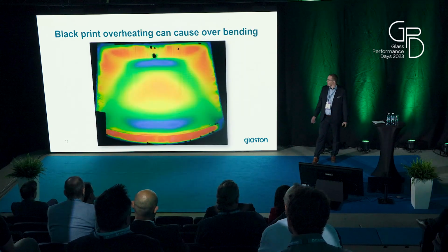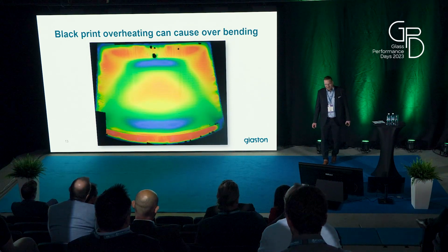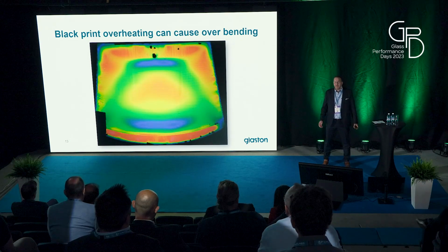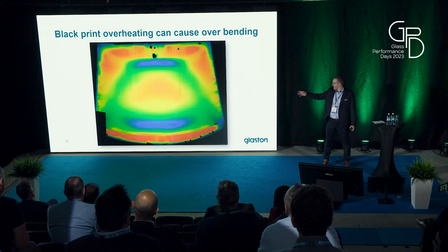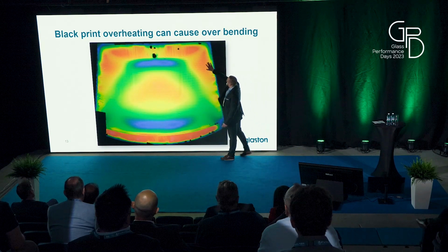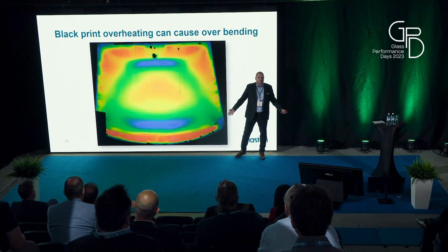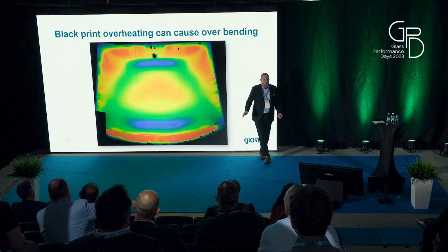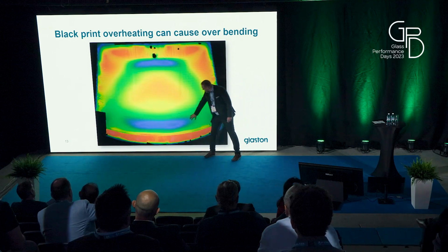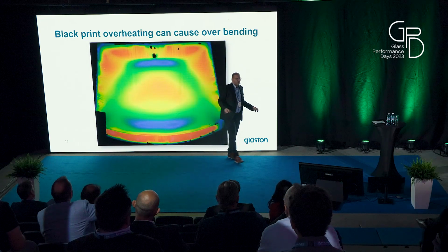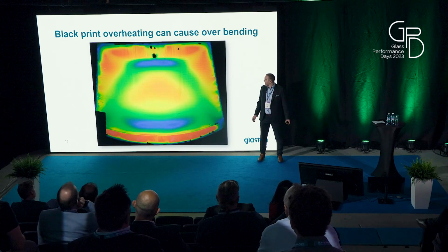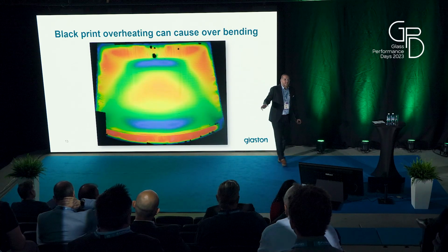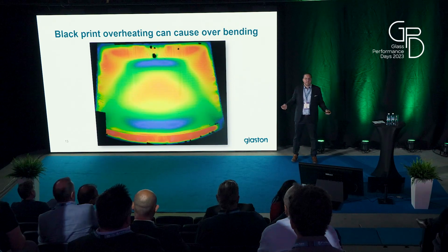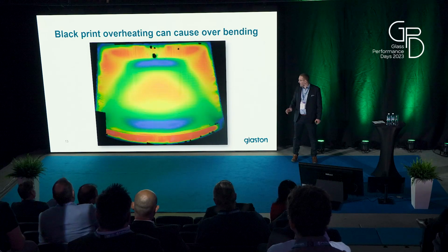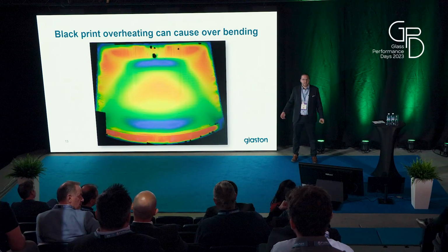Another example for testing the end quality is to compare the shape of the glass to a target shape. And in this one, orange areas at the edge are showing areas where bending has been too big. So glass has been bent during the process too much. And blue areas are the areas where glass has bent too little compared to the target. And as you can see, red areas are at the edge, and that's typically because the edges are with coated areas, painted areas, and those have been heated to a higher temperature than wanted.